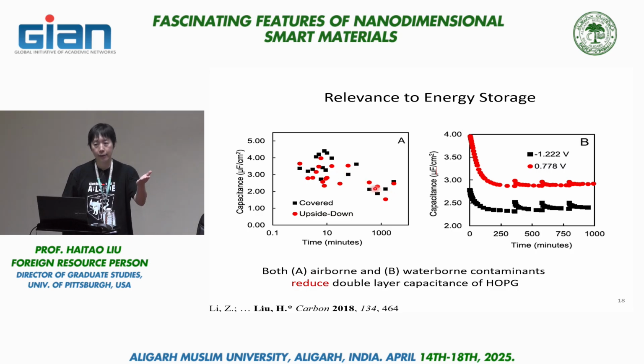They are not on the same substrate, so there's a large fluctuation of data point. But overall, you still see this very obvious trend. That is, the longer you expose your electrode in air, the more reduction of capacitance you will see. And you will see roughly 50% reduction if you leave your graphite electrode in air for about half day.